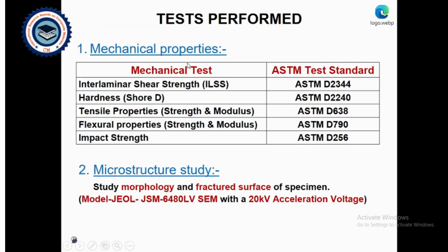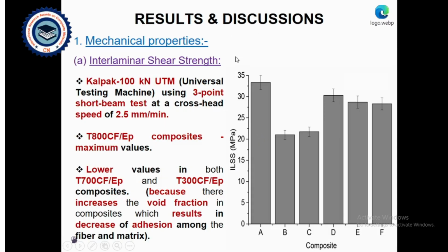Tests performed on the mechanical properties: interlaminar shear strength, hardness using Shore D hardness, tensile properties, strength and modulus, flexural properties, strength and modulus, and impact strength. The ASTM standards followed were ASTM D2344, D2240, D638, D790, D256. Microstructure study: to study morphology and fracture surface of a specimen, model JEOL JSM 6480 LV SEM with a 20 kilovolt acceleration voltage. The results and discussion, mechanical properties.